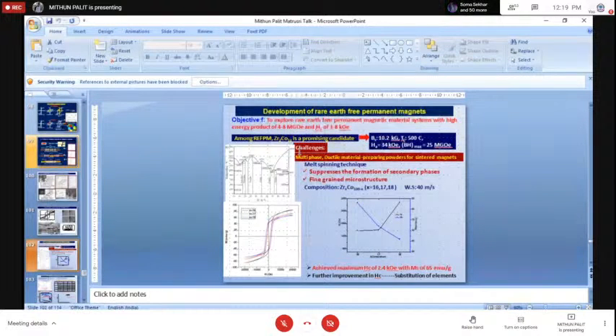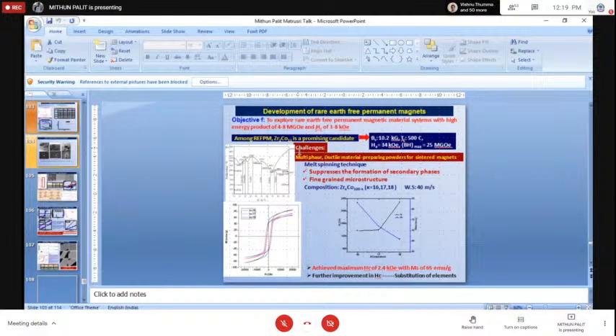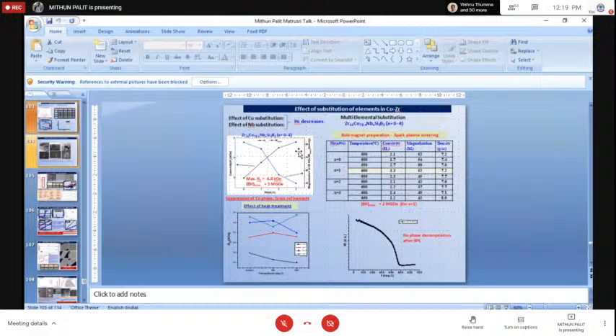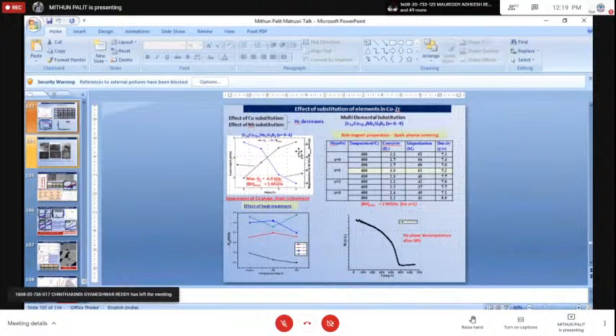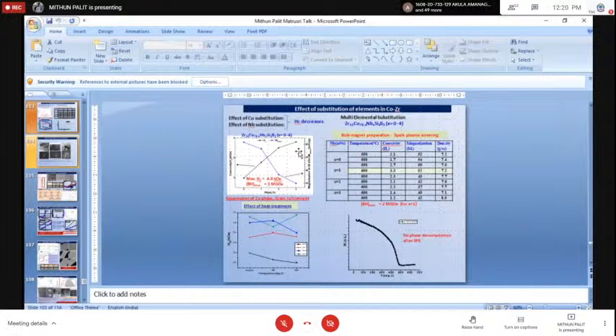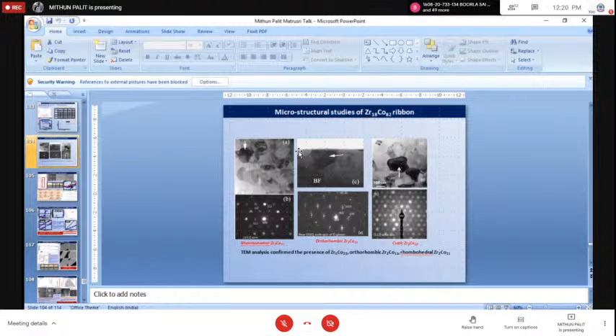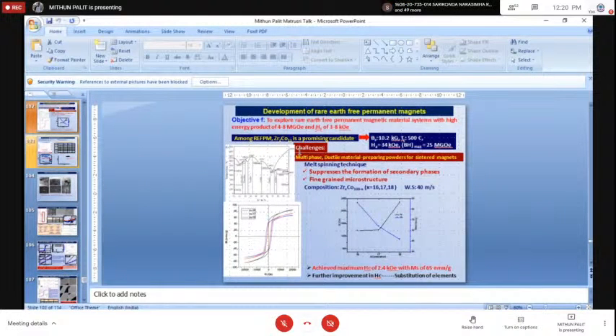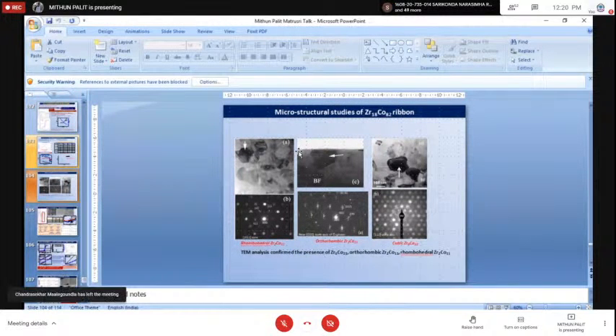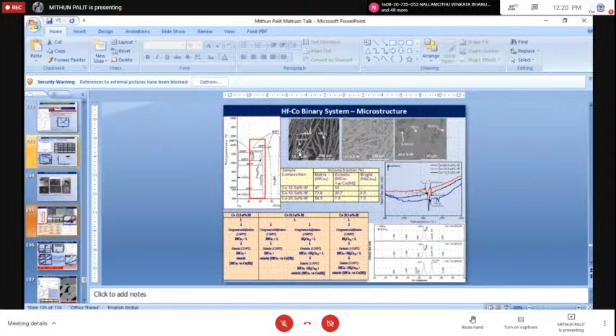In DMRL, we have studied two such permanent magnets. One is zirconium cobalt based, and the other one is hafnium cobalt based. So we have done some initial research on these classes of permanent magnet. In the zirconium cobalt, we have tried certain elemental substitutions like copper, niobium, silicon, and so on. With this, we could get a maximum energy product of nearly 3 megagauss Oersted, and coercivity up to 5 kilo Oersted. These are the transmission micrographs of these Zr-Co ribbons. If you see the phase diagram here, the phase which is responsible for hard magnetic property is a high temperature phase, and therefore to stabilize it we have to carry out non-equilibrium solidification processing such as melt spinning. These are the microstructures for them, and again microstructural study is important there.